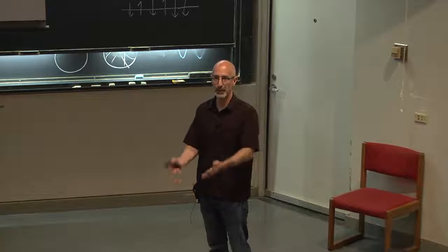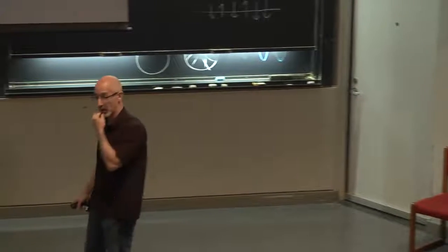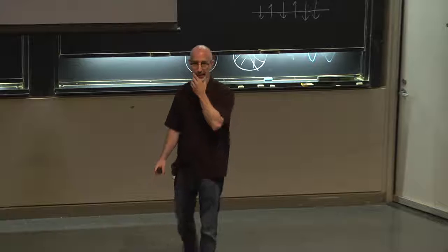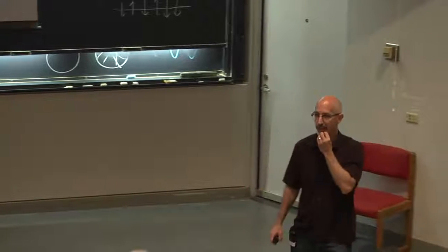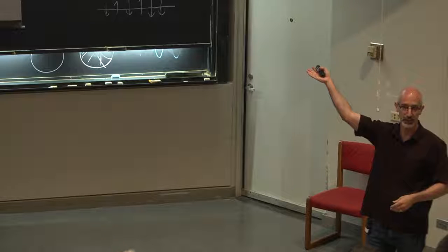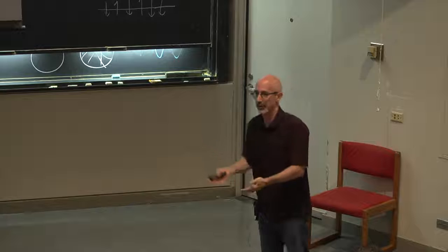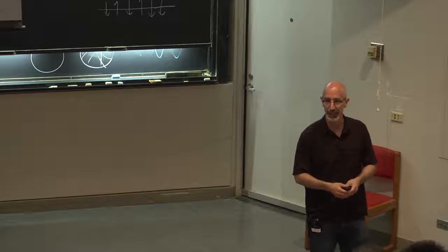So the particle hopping or the activated processes, which Jorge alluded to, that are hard to get in the infinite dimensional kinds of solutions that you have, are naturally put in by hand in these models. And so that's why things like Stokes-Einstein violation come out naturally in these kinds of pictures, which is very nice. It's actually not so trivial to get Stokes-Einstein violation in a realistic way from the d equals infinity solution, as far as I know.